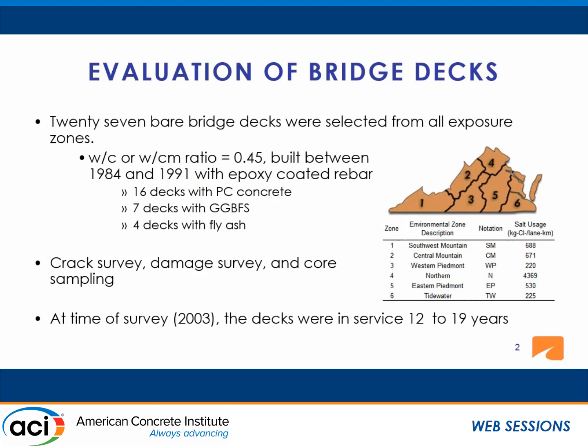Since we only have a short amount of experience with the corrosion-resistant reinforcement, we chose bridges with different types of reinforcement, but the concrete used has been similar to what we use today. So we have 27 bare bridge decks without any overlays, selected from all the exposure zones, as we call them. They are created based on the de-icing salt usage in Virginia. And we had bridges from all of these six environmental zones. Out of the 27, 16 had plain cement concrete, and 11 had supplementary cementitious materials.